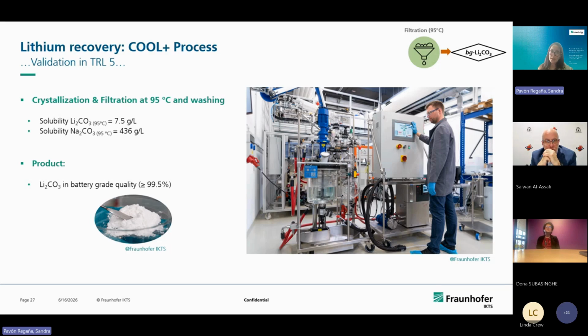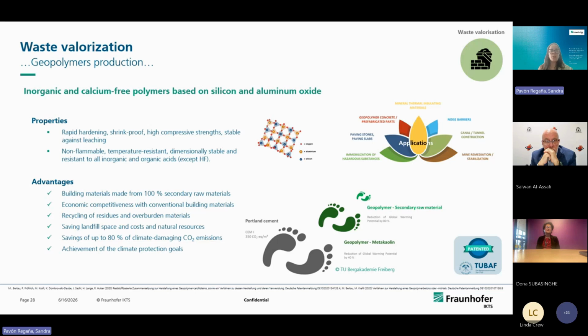It's not a problem for us to add sodium carbonate because we can consider the solubility of sodium carbonate and lithium carbonate, and that is why we are able to get lithium carbonate in battery grade, with purity of more than 99.5%. Now the question is, okay, Sandra, great, you are able to get lithium carbonate in battery grade, but lithium is 3% of the input material. What are we going to do with the rest? So that is why we are going through this concept of geopolymer production.